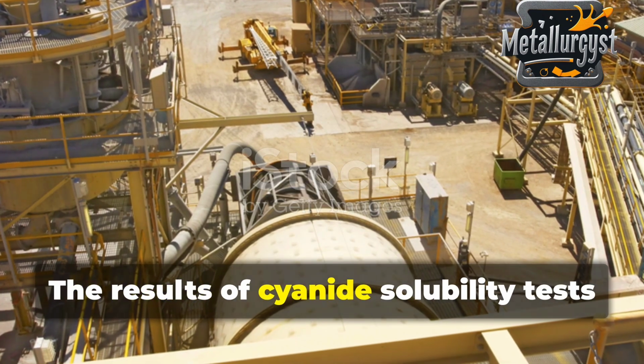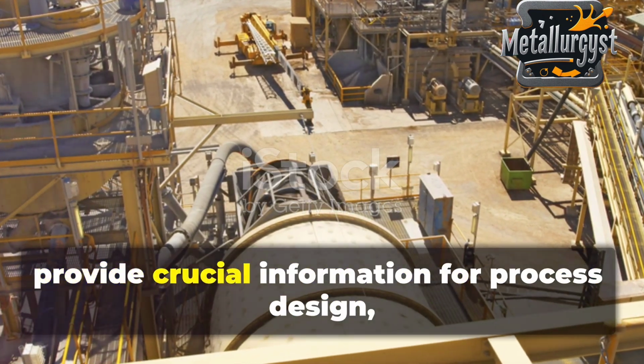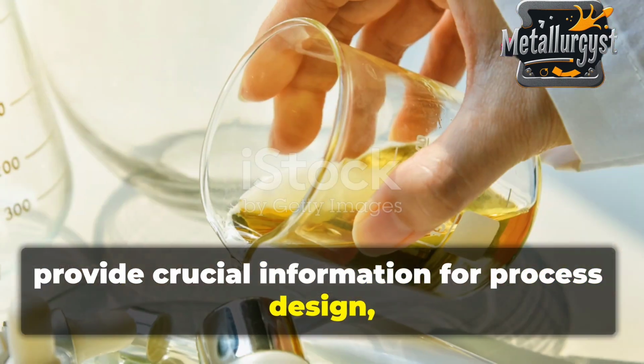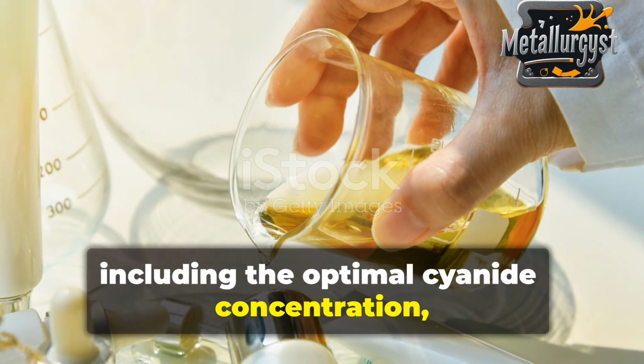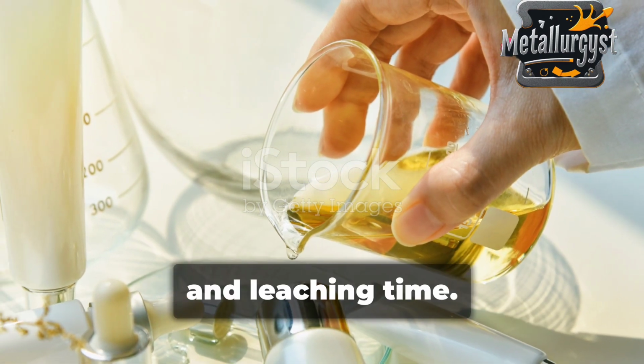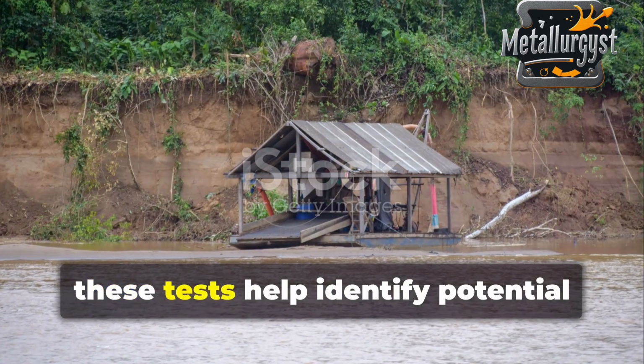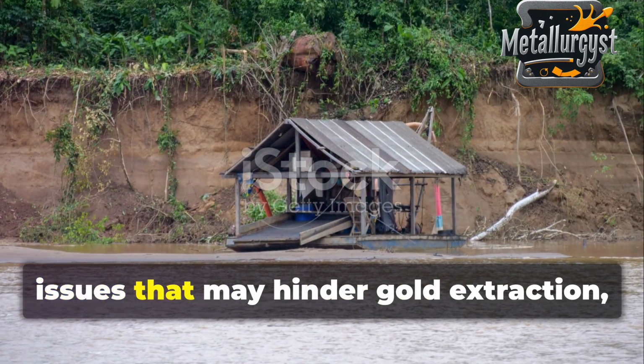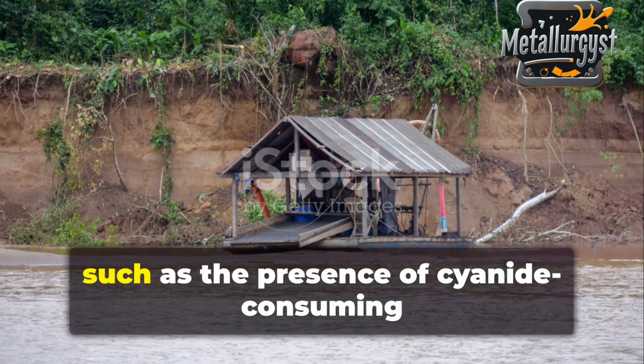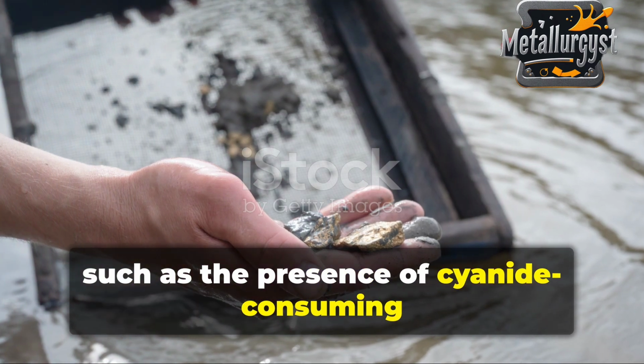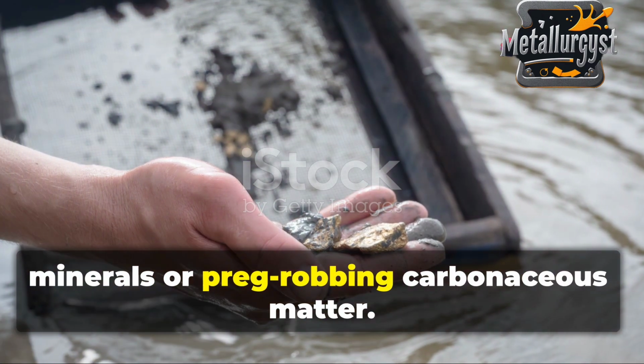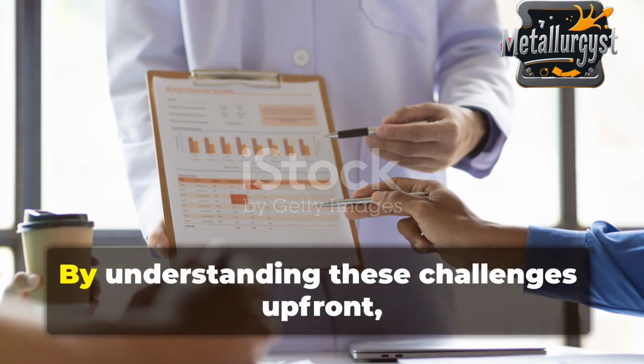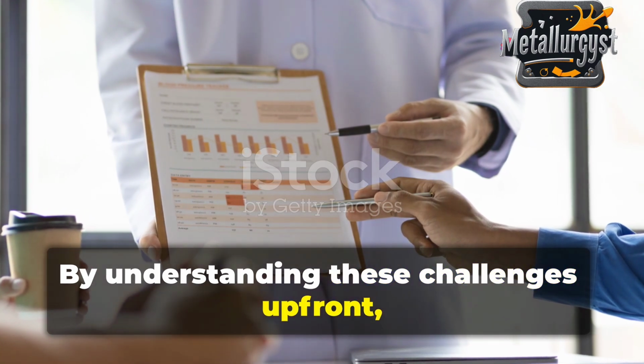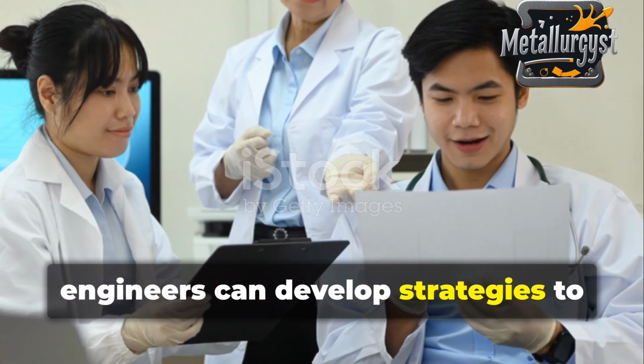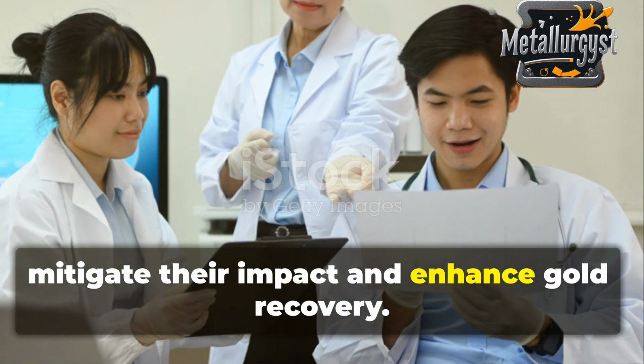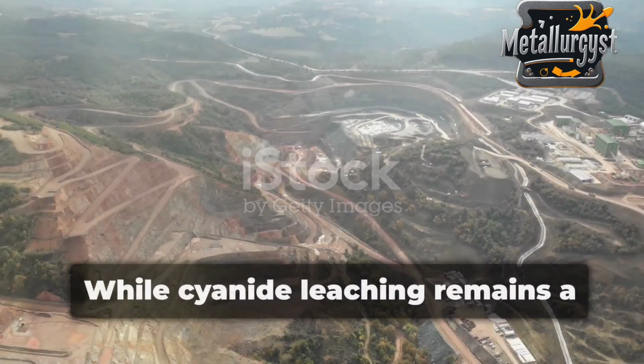The results of cyanide solubility tests provide crucial information for process design, including the optimal cyanide concentration, pH, temperature, and leaching time. Moreover, these tests help identify potential issues that may hinder gold extraction, such as the presence of cyanide-consuming minerals or preg-robbing carbonaceous matter. By understanding these challenges up front, engineers can develop strategies to mitigate their impact and enhance gold recovery.